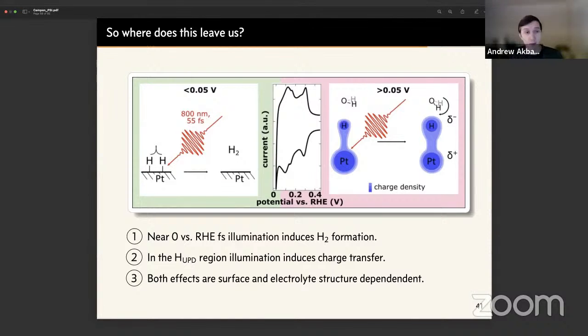Okay. I guess the time is almost up, so maybe I will just ask the last question that I have, because I think you mentioned at the beginning, and I'm just curious about your opinion. You mentioned that the electronic structure of the bulk solid is important. It's certainly the case, but when you come to the surface, there could be surface states, a surface electronic structure, which might be quite different from the bulk. We know this from different materials, not only metals. Now, if it comes to photoemission experiments in UHV conditions, we can probe the photoelectrons, and depending on the angle, we can deduce the Fermi surface, the k vector, and so on of the electrons going out. Now, this is the state of the art of how we can study the electronic structure of the surface.